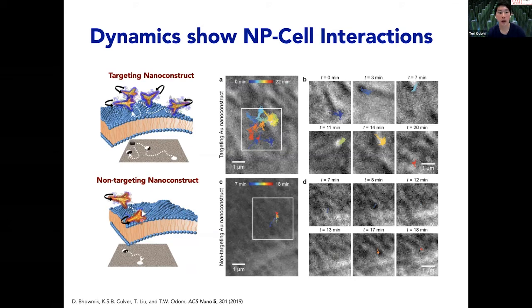to HER2. So if you take a look at the area of span, translationally, how much of an area does it take on the surface, you can already see that it looks quite different if you have a targeting construct versus a non-targeting construct. And you can see how it's localized in different positions within this box for the targeting case, and then it's fairly localized in the non-targeting case.